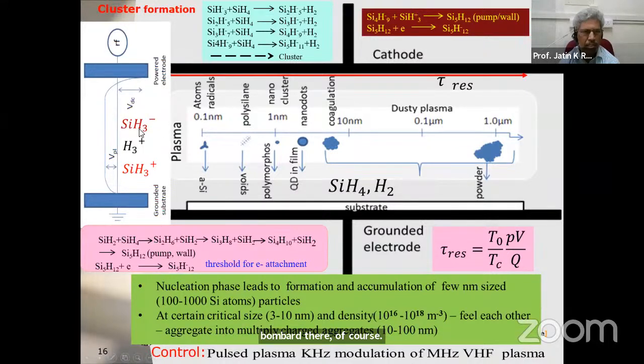Now, what happens is that this negative charge, SiH3 minus, for example, once it's inside, will interact with another silane. So they'll produce Si2H5 minus. Si2H5 minus will again react with silane. It will keep on increasing and become a cluster. This cluster will still be trapped unless it reacts with another positive ion, then it becomes neutral and goes to the wall. That means it will go to the substrate. But it can also pick up another electron here and still get trapped. You can also get neutral reactions like SiH2 radicals, and SiH4 can also go on up to become clusters.